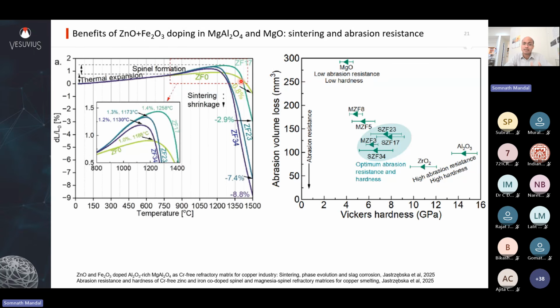Here you see pressed pellet dilatometry. Without spinel doping, you see the shrinkage at 1500 is only 0.8%. With more and more doping, the shrinkage is increasing, meaning you are getting better and better sintering. And then the sintering expansion is also less with more doping, which is always beneficial to have a low porosity, high density material. Not only that, your abrasion resistance also increases.